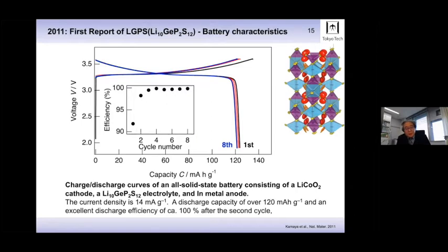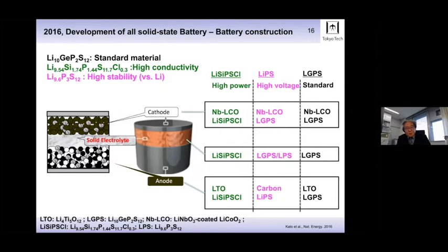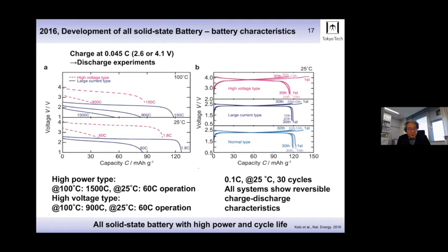The charge-discharge characteristics are similar to those of liquid batteries, but it was really surprising for a solid-state battery at that time. This is the battery structure, the test cell structure. The advantage of the solid-state type battery is that we can change the combination of electrode and electrolyte in one cell. Using this advantage, we can construct the test cell and measure the battery characteristics. And here is the charge-discharge characteristic of the solid-state battery, with very high current densities found to be possible at 100 degrees C and at room temperature without any problem in cycling.